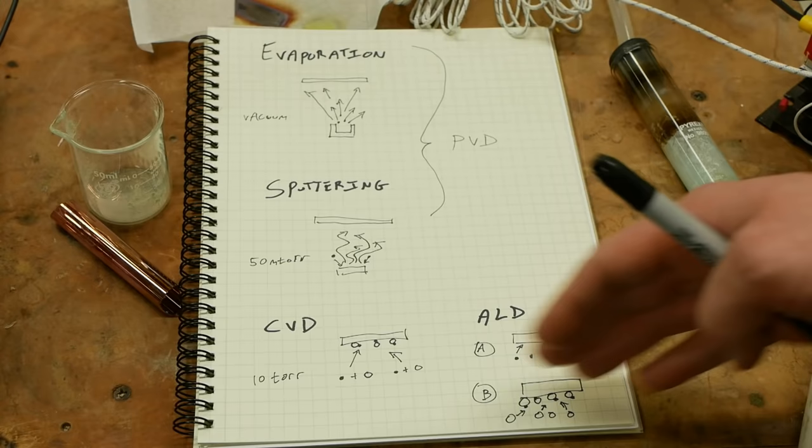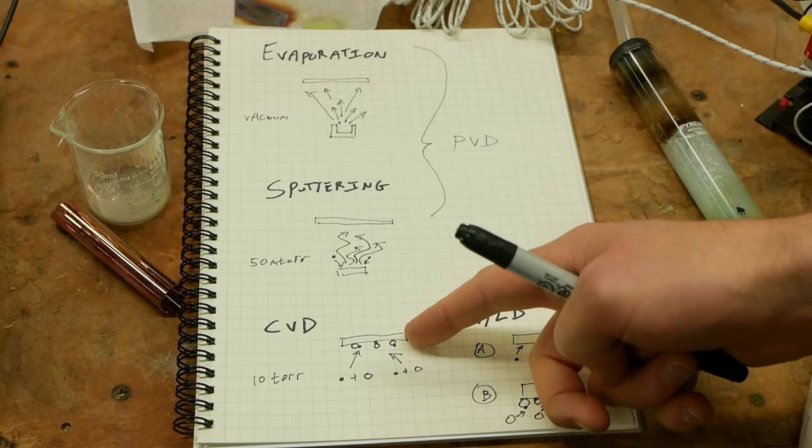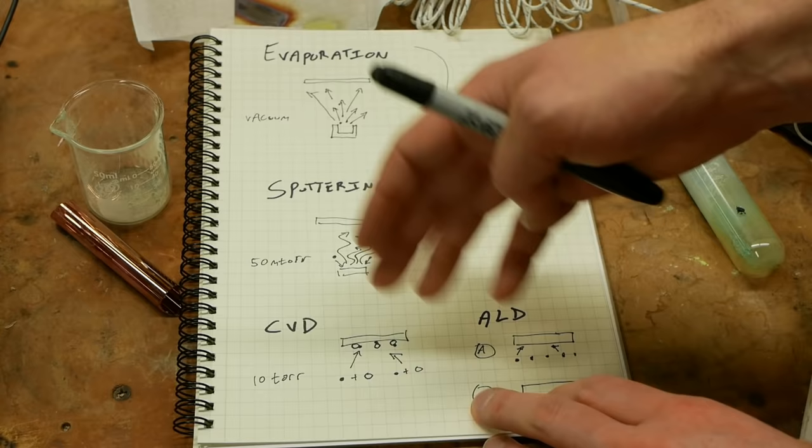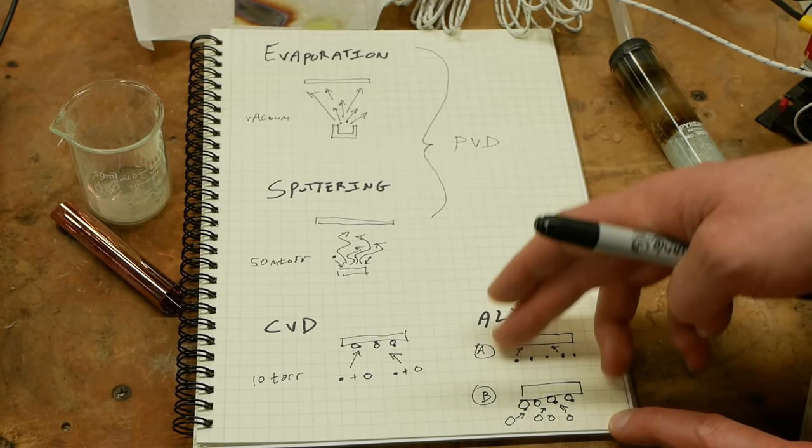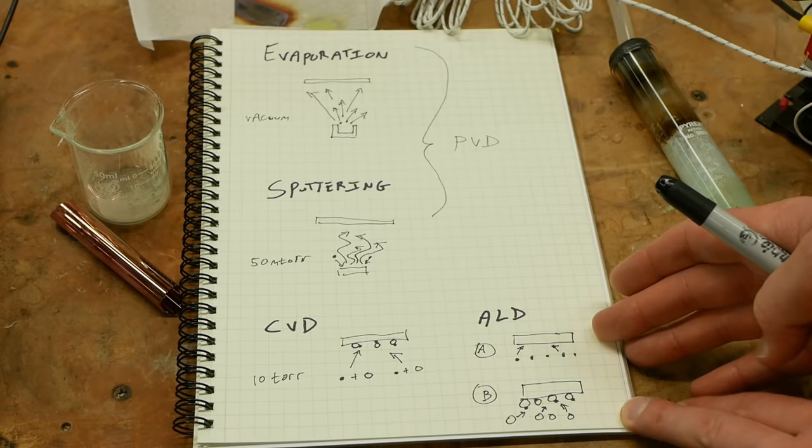So every time you go through an AB cycle, you end up with one more atomic layer of whatever we want. So you can see the difference here. If there were a really deep hole, like a blind hole in the substrate, with CVD, what might happen is these process gases get in there and they get used up at like the top of the hole. So they never really get down to the bottom of the blind hole because they're reacting with each other and it's depositing the material as quickly as it can get to the surface. But with ALD, since each gas only forms a monolayer, then we can take as much time as we need for the gas to diffuse down to a deep hole and it's just truly perfectly uniform, at least in theory it is.